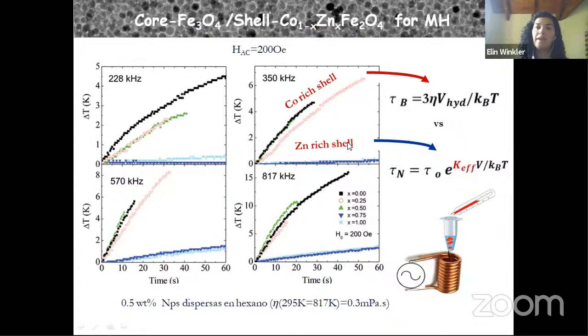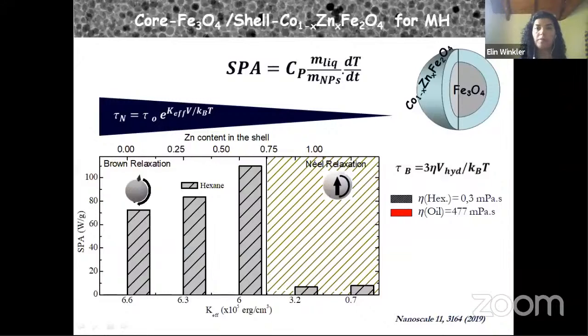So in this case, we have a change of relaxation mechanism. We can quantify the specific power absorption in this way. This is a conventional way to do that, where it is proportional to the specific heat and the heating temperature with the time. And we observe that the three samples have a very large specific power absorption. On the contrary, when we replace the cobalt by zinc, the specific power absorption is reduced.